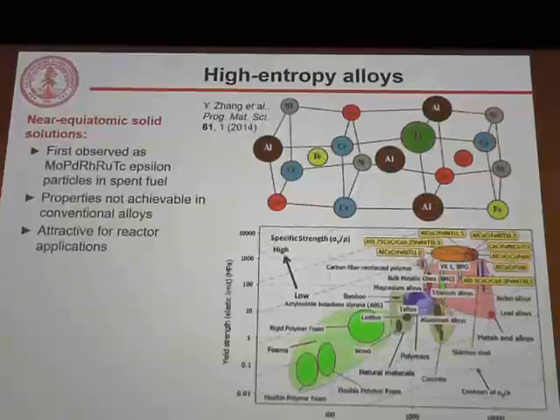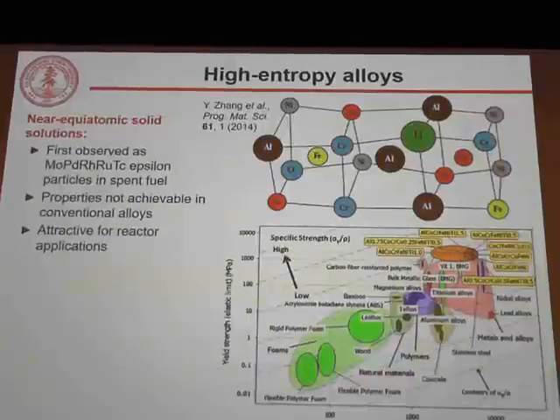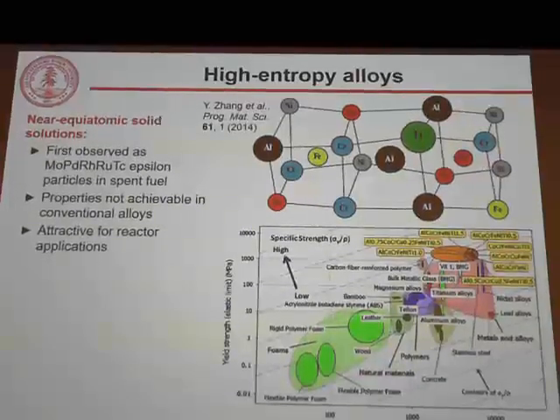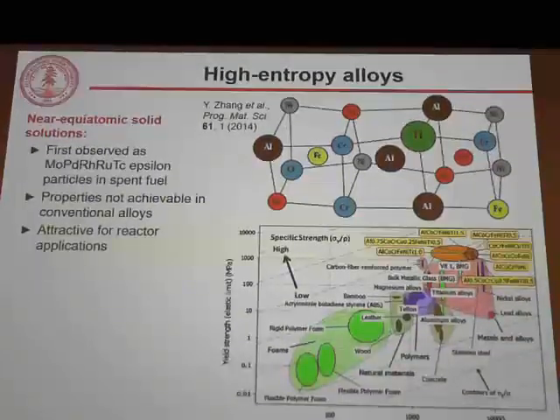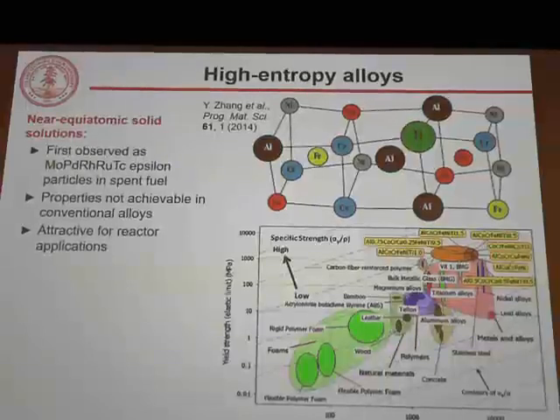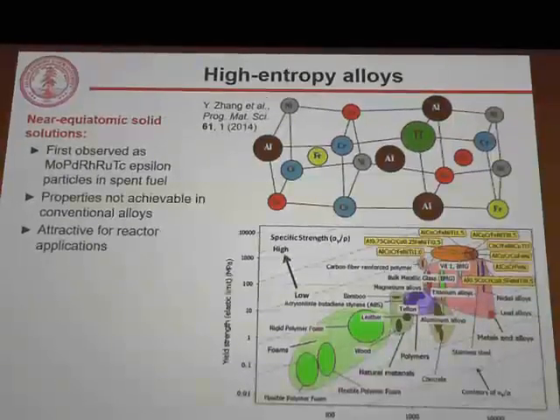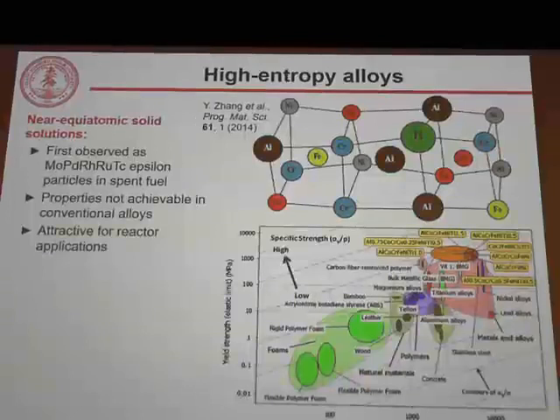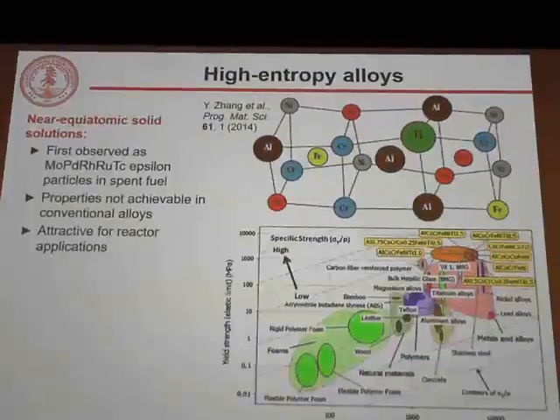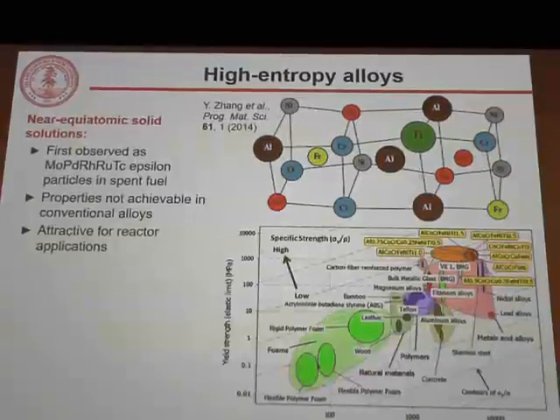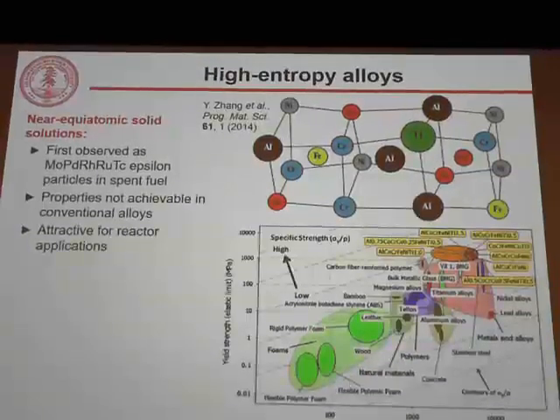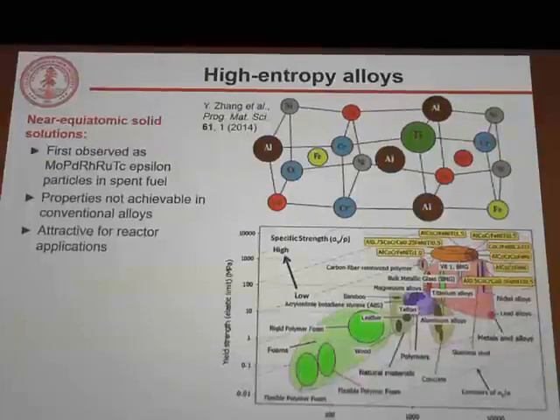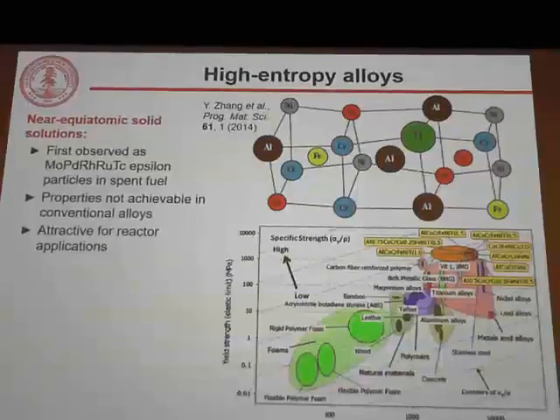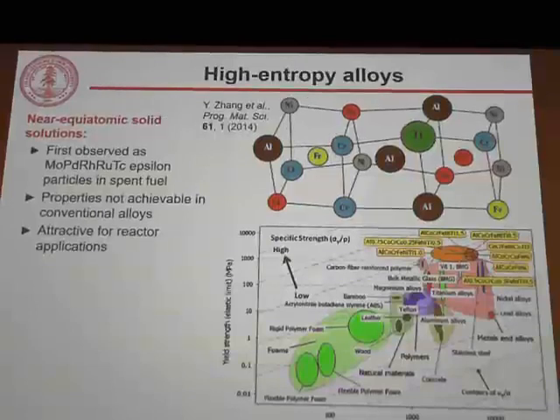Another system I've looked at are metals, high-entropy alloys, which are near equiatomic solid solutions of 5 or more metal components. So these are a recently discovered class of material, or I should say recently used in engineering applications. They were first discovered in nuclear fuels as epsilon particles, but only within the last decade or so has it been recognized that they have really unique properties. So I show here in the lower right the specific strength of different materials, and you see that the high entropy alloys in this orange blob have specific strengths superior to that of virtually all conventional metals and alloys in this red blob. So they have nice properties that are in many cases attractive for reactor applications.